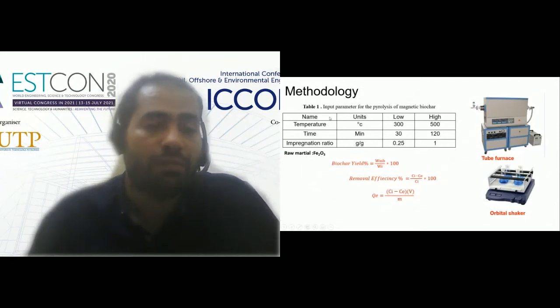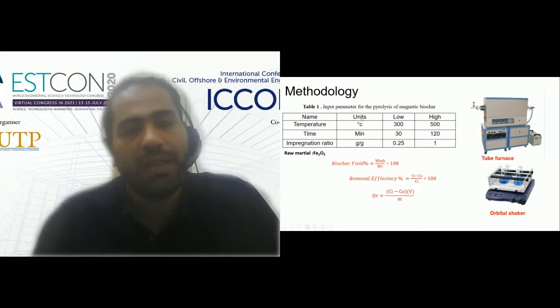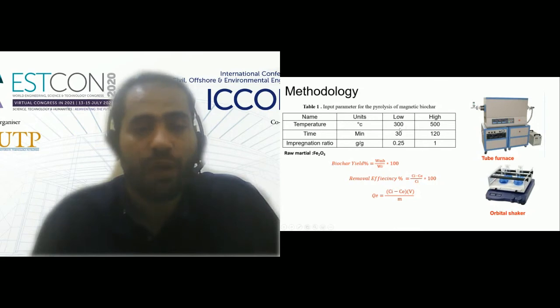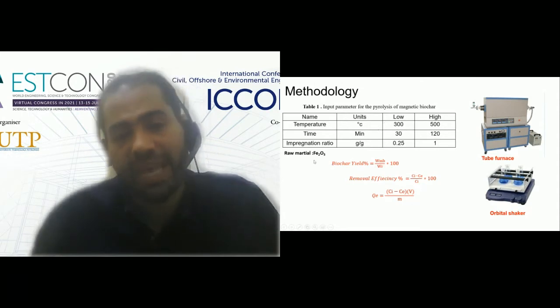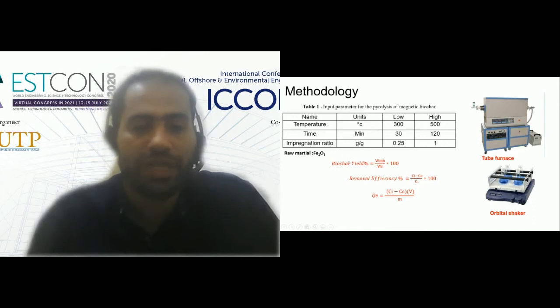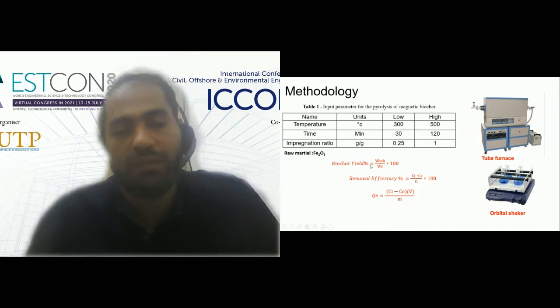We have three types of input parameters: temperature, time, and impregnation ratio from the material to iron oxide. We have the low temperature and high temperature. We selected the time and the impregnation ratio from a previous study, while the temperature for rice husk we determined using thermogravimetric analysis. We also have the theoretical background on biochar. How can we find the biochar yield? We use this equation, and removal efficiency using these equations, and also adsorption capacity.